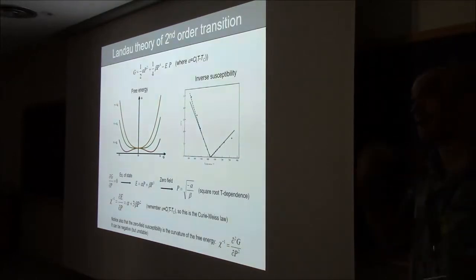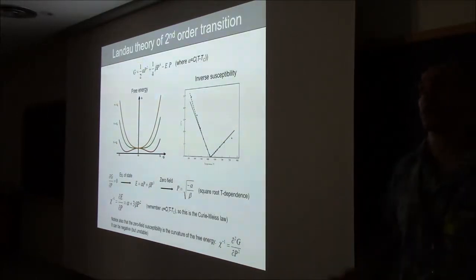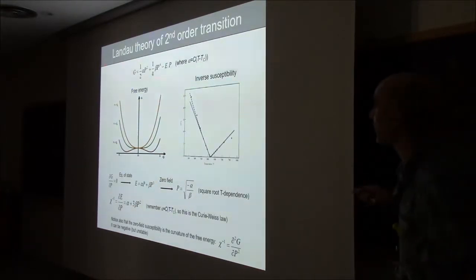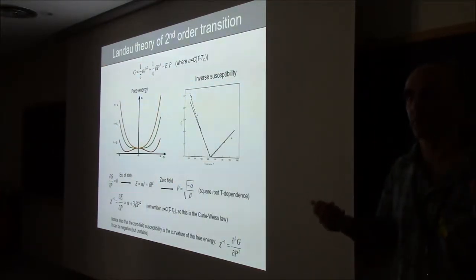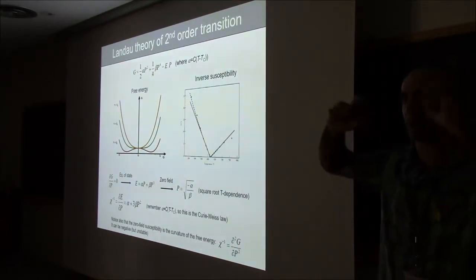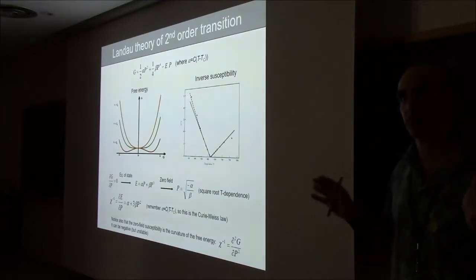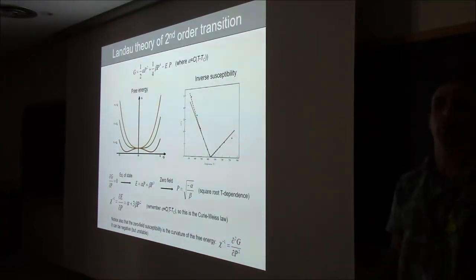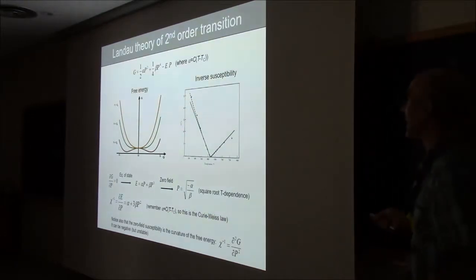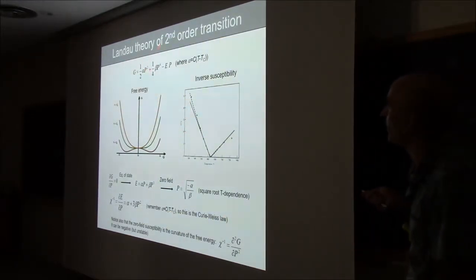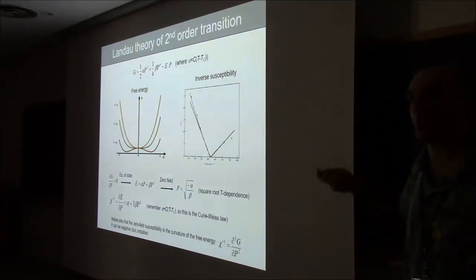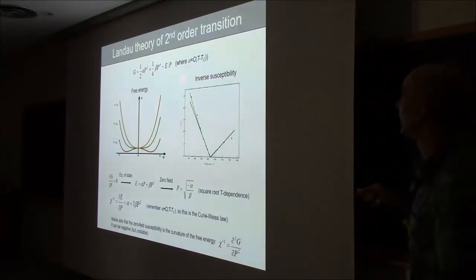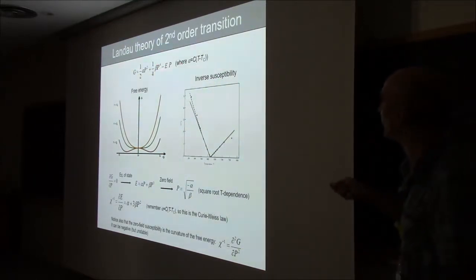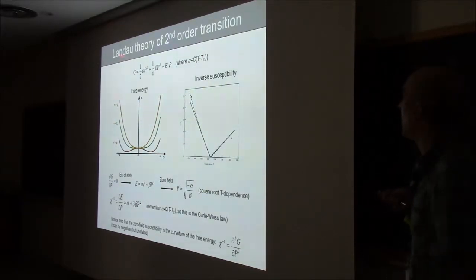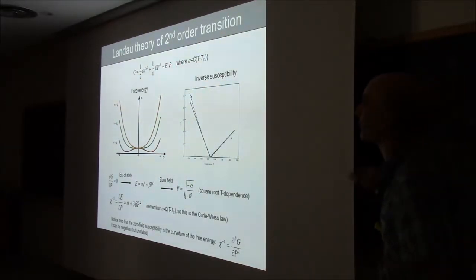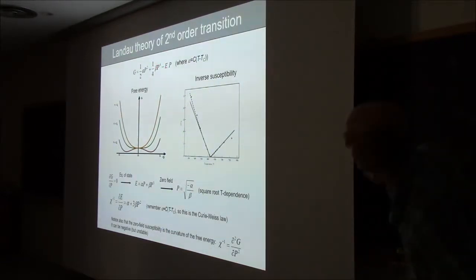So if the high symmetry phase of your material is cubic, centrosymmetric, then in this Taylor expansion you cannot have any odd parity terms. If I invert space, the free energy cannot change in the cubic phase. Once you are in the polar phase it will obviously change, but in the cubic phase it cannot. Since this has to describe both, I can only put terms like P squared, P fourth, P sixth. I cannot put P or P cubed. You can break that symmetry if you apply an electric field, and then the coupling between the electric field and the polarization is linear. If the polarization is parallel to the electric field, the energy will go down, and that's why you put a minus here.